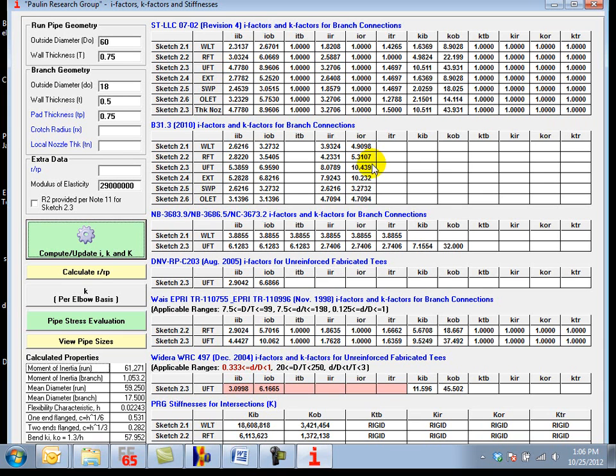B31.3 would give us a value of 10.4. 0702 would recommend 1. The nuclear code would only recommend 2.7. And Weiss would recommend 1. So what this suggests is that B31 is overestimating the stress at the branch connection by a factor of around 10. It would definitely be a waste to have to reroute any pipe because of an out-of-plane overstress at this branch connection.